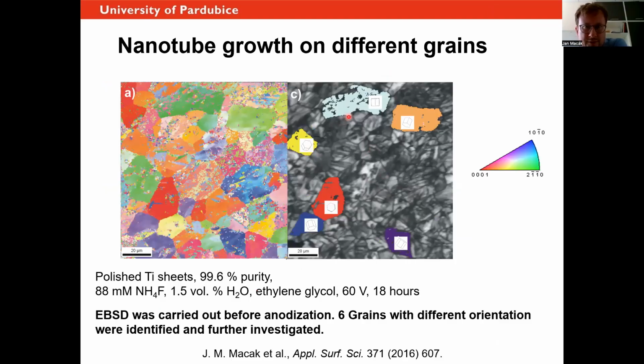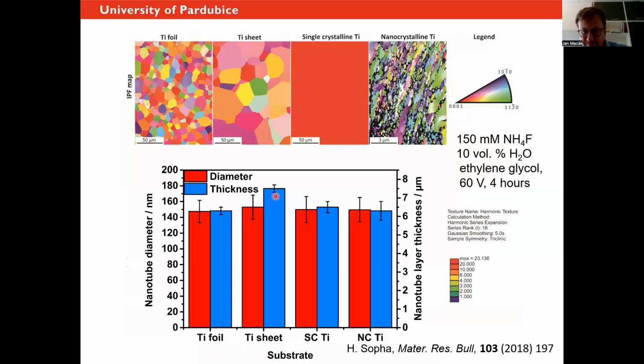We did some inspection by really proper EBSD and TEM analysis on grains with different orientation. And there are on the surface definitely grains with very different orientation. And the good news is that the tubes still grow. So in principle, it's absolutely not depending on the grain orientation or on the grain size.